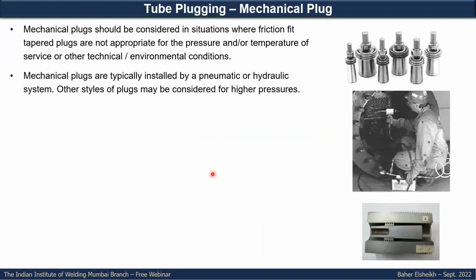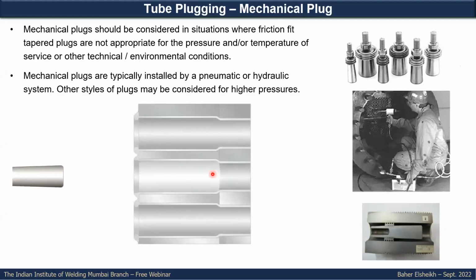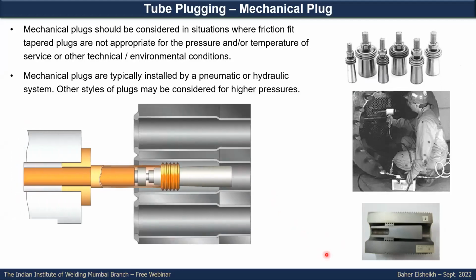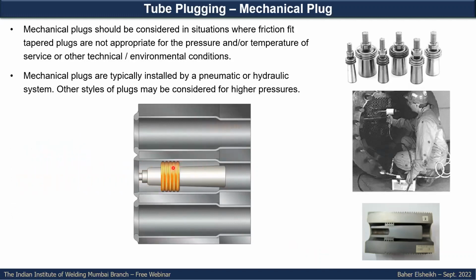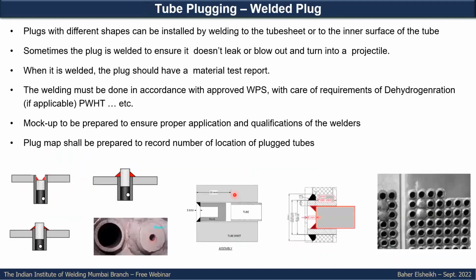This mechanical plug is recommended or can be used for higher pressure applications. You can see here from this illustrative graphic how it is applied. It is inserted. Then by hydraulic machine, the inner part is pulled like that, and while pulling, this is covered, it is like a labyrinth. This labyrinth will be sealed against the tube and force the tube also to seal against the tube sheet.